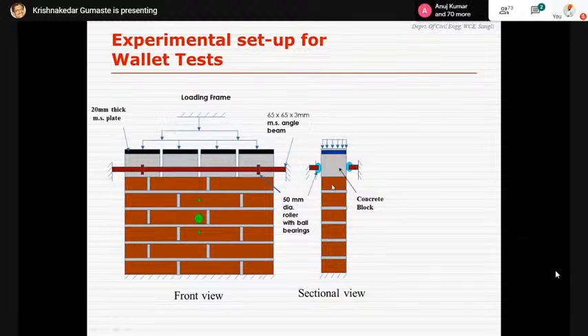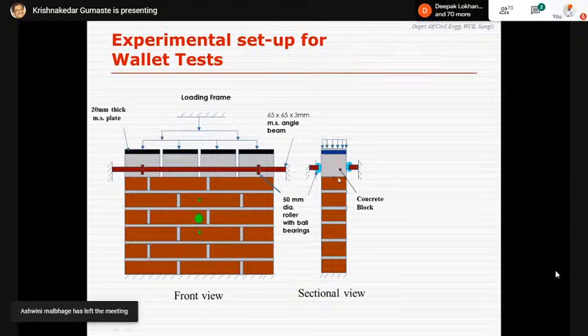If the bricks and mortar are of very high strength, it was observed that the wall tries to topple down rather than get crushed, and the realistic compressive strength does not occur, and thereby two rollers are fixed. Why I am highlighting this is that these are some of the experimental studies we need to concentrate on, with moderate strength bricks that we get in our areas, which is something we need to explore further.